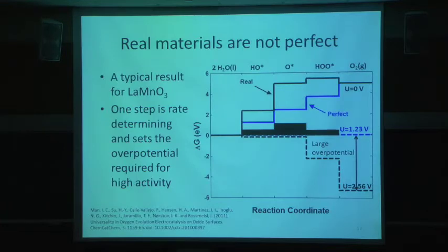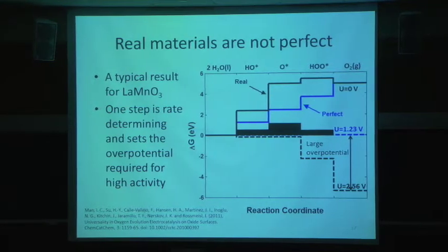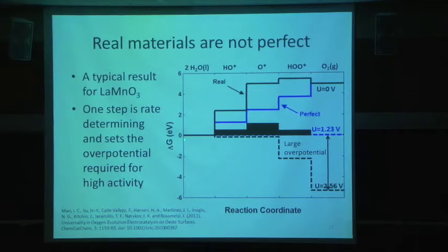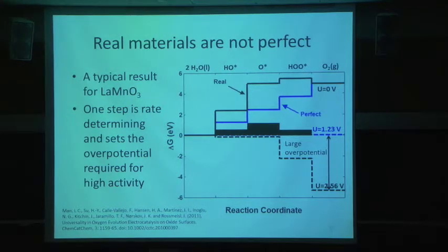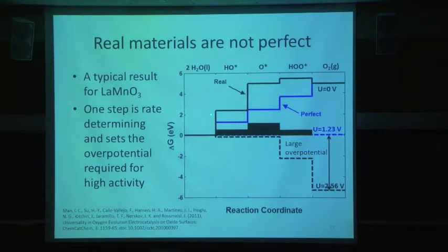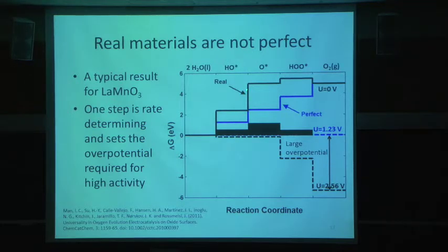Okay, so what does a perfect material look like? So again, the blue line here is what a perfect catalyst would look like. As you apply 1.23 volts, the reaction is perfectly thermoneutral. A real catalyst might be this black line. So you can see this step is too high, this step is too high, these steps are too small. The consequence of that is when you apply 1.23 volts to this catalyst, this point still comes down to here, but now you have to go up in energy and come back down to be thermoneutral.